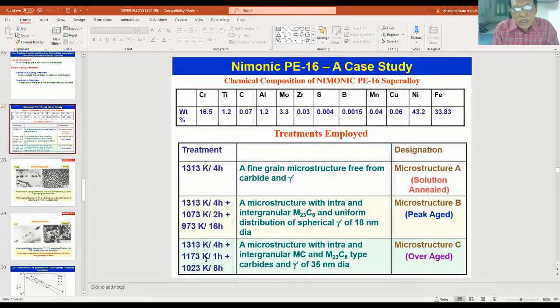Intermediate aging treatment of 900 gives you MC type of carbides, titanium carbide. For me at 800, the MC titanium carbide is not present. That means the intermediate aging temperature dictates the type of precipitate formed. Then finally, here I have 700 degrees centigrade, but here it's 50 degrees centigrade higher, a slightly higher temperature for gamma prime precipitation.